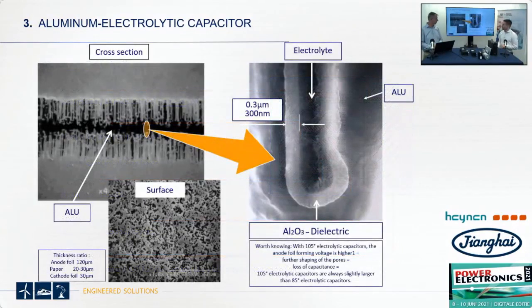So, this is one hole of the capacitor, and there you can see why we have limits to generate a capacitor with a high voltage resistance. When you produce the capacitor, you have in the first step a raw material, aluminum foil, and then you etch the holes inside to increase the surface of the plate of the capacitor, and then you grow up the oxide layer. When you make the oxide layer too thick, then you close the holes, and then you have only two plates and not the big surface of each hole. And there is the limit of the capacitor technology.